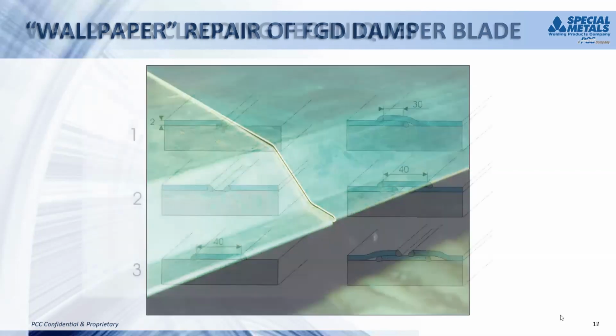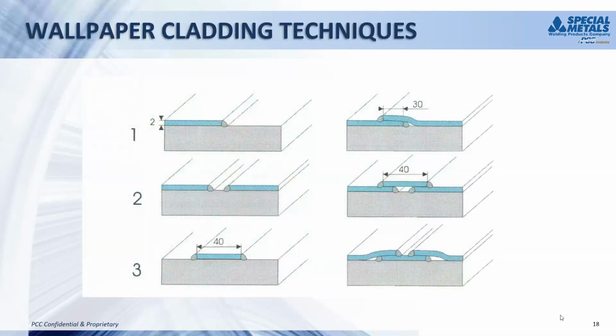This slide shows the various techniques that can be used for wallpapering. The objective here is to be sure that the surface weld is not exposed to iron dilution. In the first scenario, you see the sheet has been welded to the steel substrate, and that weld obviously will be diluted with iron. But the next weld, the sheet would overlap the existing sheet, and that weld would be an alloy to alloy weld. So the surface weld is not diluted with iron.